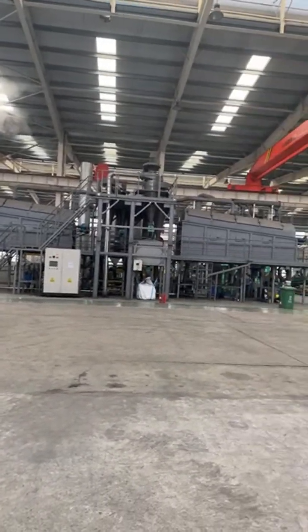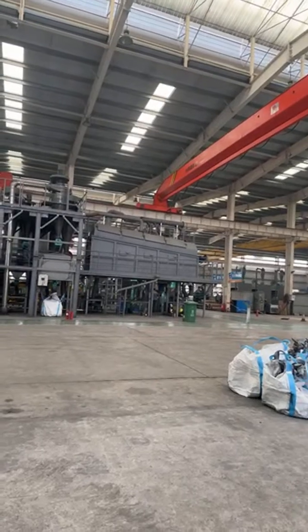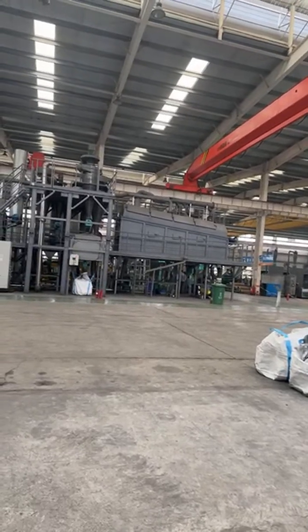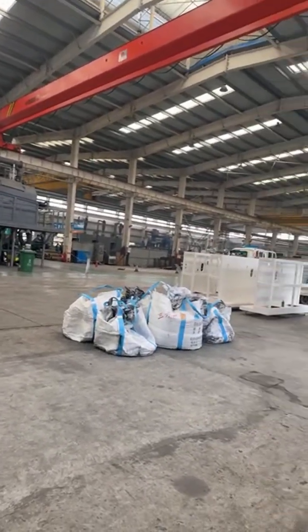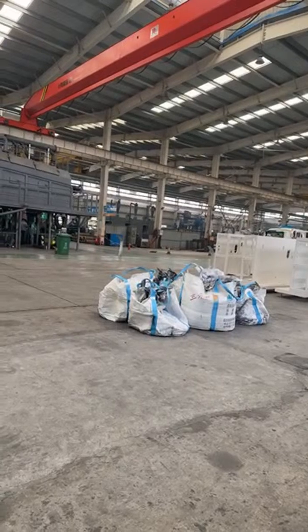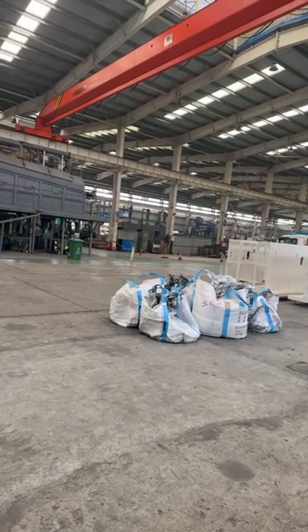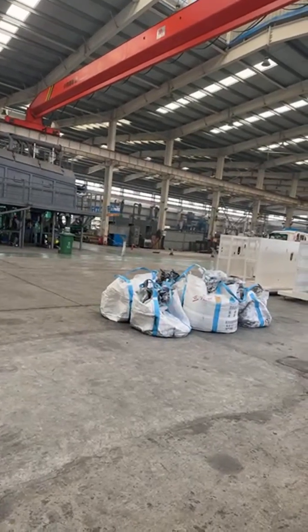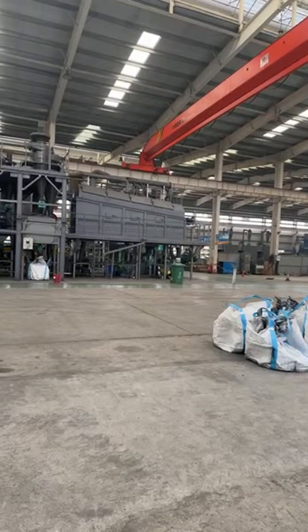After crushing, the carbonized anode and cathode materials can be actively peeled off from the metal. The metal and anode powder can then be preliminarily separated by vibration screening based on the size and shape differences between particles. The complete set of equipment operates under negative pressure without dust or spillage, and the separation efficiency can reach over 98%.